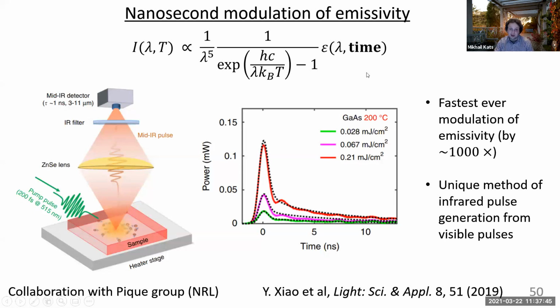By the way, what I described here is a very naive picture. There's actually much more complicated stuff going on. And if you take a look at the supplementary information of this paper in Light: Science and Applications, we spent a long time building a pretty complicated multi-physics model because, for example, this is one of the cases where the lattice temperature and the electron temperature are very different for a short amount of time. The first thing you do when you hit it with this pulse, these are very high energy pulses, and very short, just hundreds of femtoseconds, you end up heating the electrons up to about 4,000 degrees, whereas the lattice remains at about 200 degrees Celsius. So you have this kind of multiple temperature object, and it's really only the free carriers that are emitting.